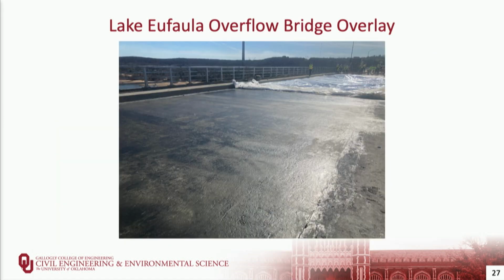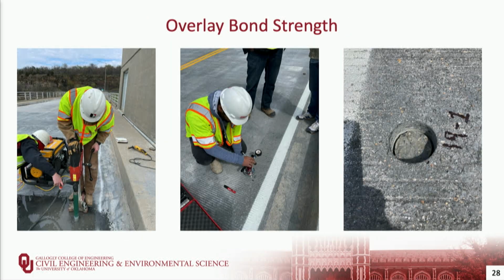This is a picture of the finished overlay immediately after placement. This is actually one of the worst looking sections of the overlay because it was the first they placed, and it still has a very uniform surface and ended up very smooth. They came back in, grooved the surface, and then we came back out and did bond pull-off tests on the overlay, partly for their quality assurance plan, but also to look at bond in different locations of the overlay.